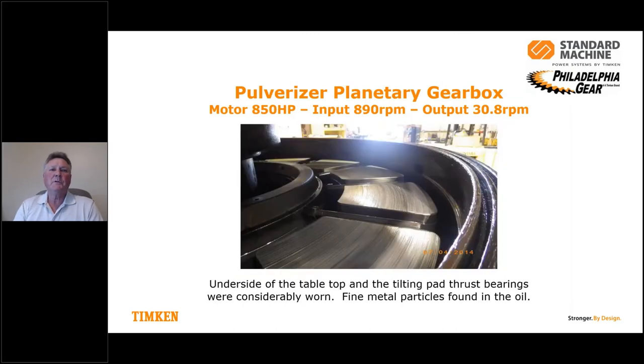The next thing we did is we took the top cover off, which is the rotating cover. The cover basically rests on these tilting pads, and there's supposed to be a sliding action, but there's supposed to be a lubricating film that separates the two. And this type of wear that you see in this picture was not normal, it was abnormal. There were a lot of fine particles found in the oil, and they were very worn. You can see the amount of damage on these thrust pads.